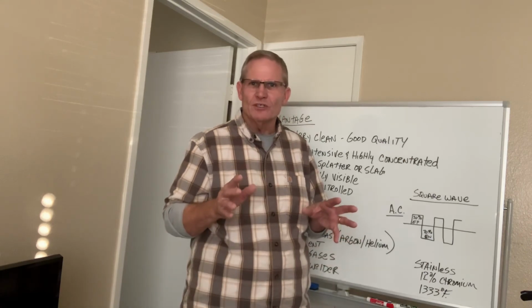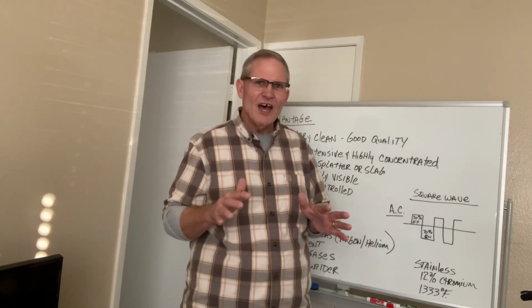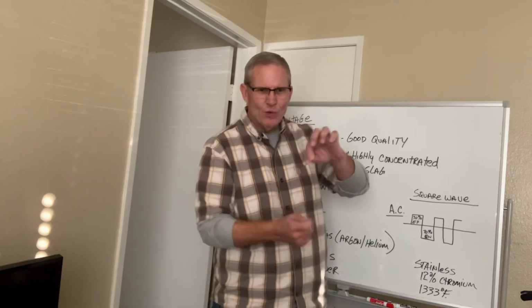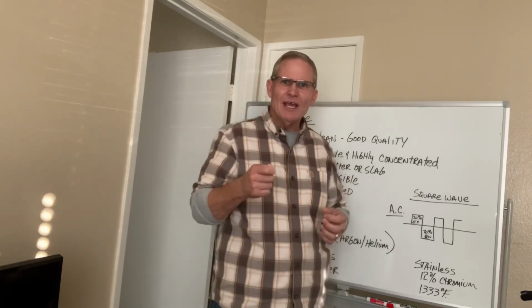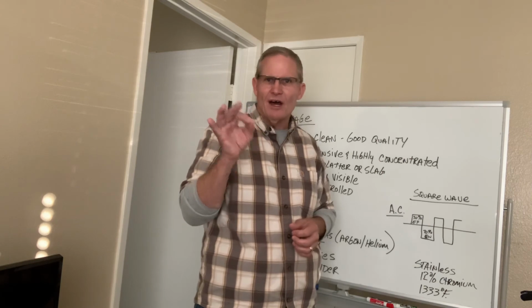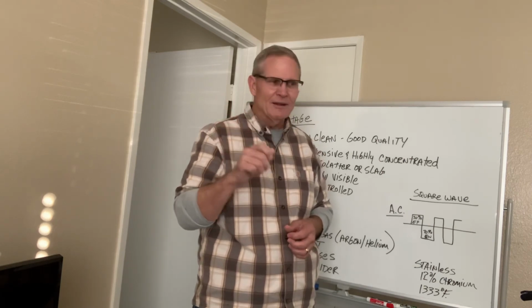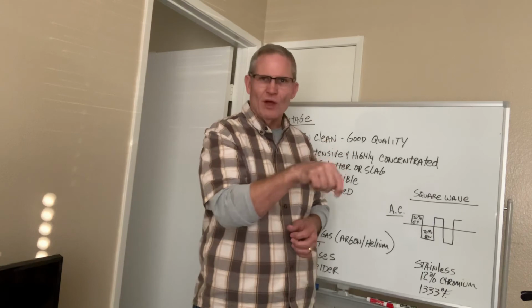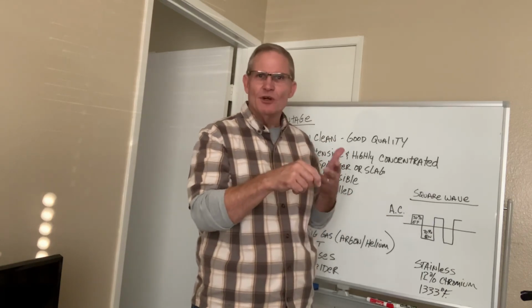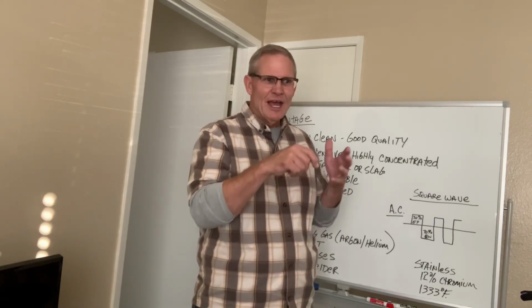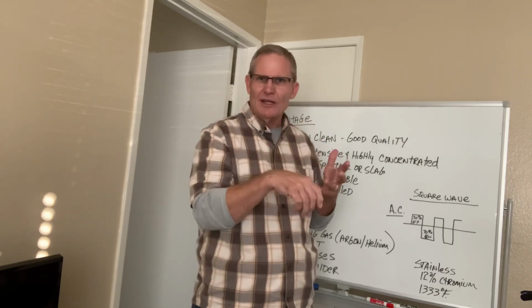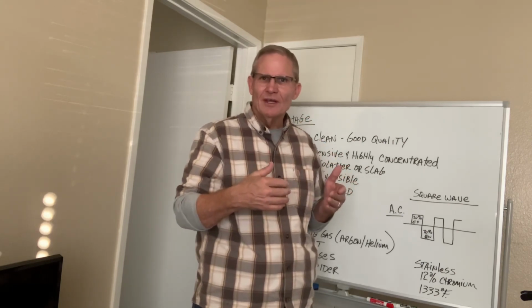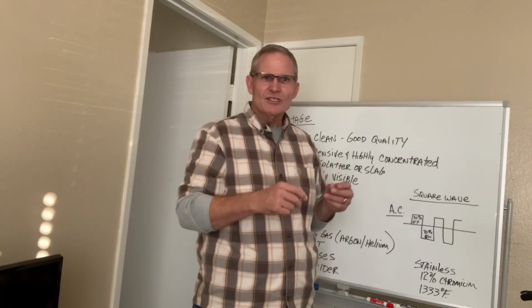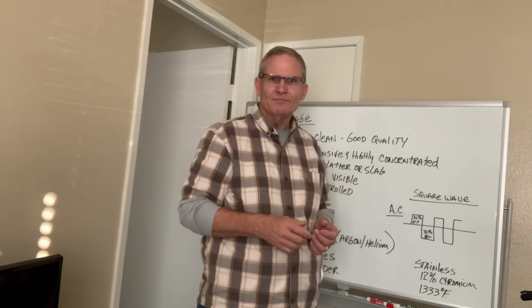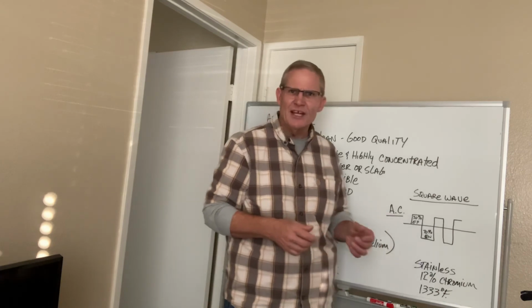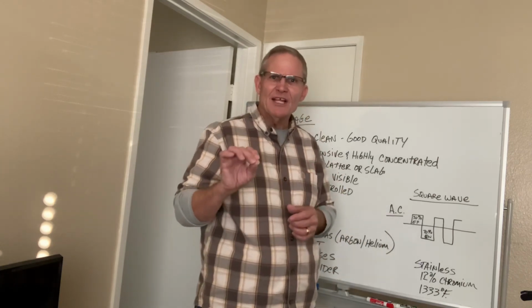Typically in welding procedures, when you're welding stainless, they hold it to 500 degrees Fahrenheit, meaning you run a pass, and then you typically have a temp stick. It looks like a crayon, but it melts at 500 degrees Fahrenheit. You just mark it on the metal right next to the weld zone. If it melts, that means you're above 500 degrees Fahrenheit. If it makes a chalk mark, you're not at the 500 degree mark, so you can go ahead and continue welding. So it's not uncommon when you're welding stainless and you're welding multiple layers to have a temp stick with you and to check it.